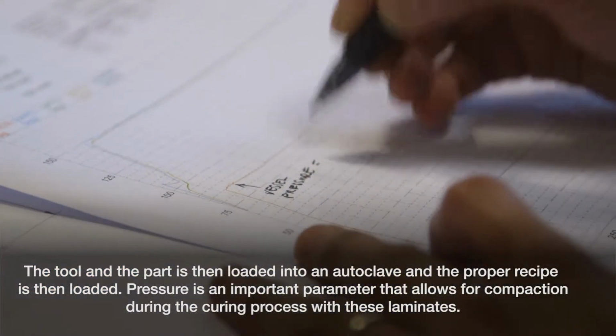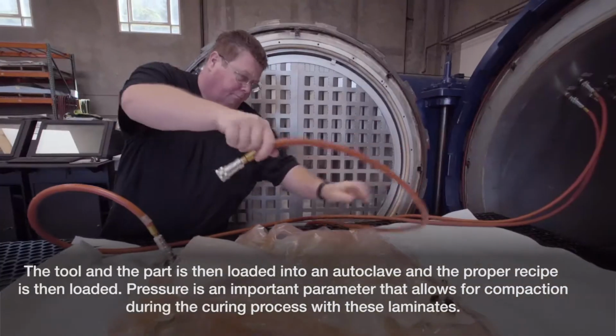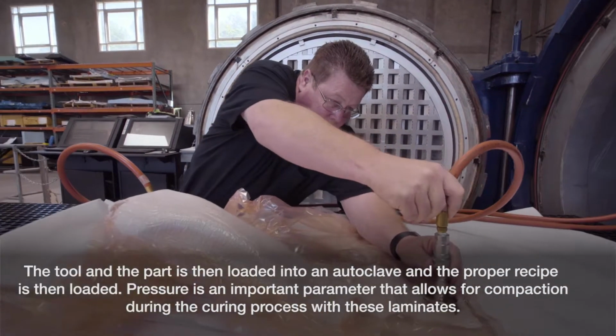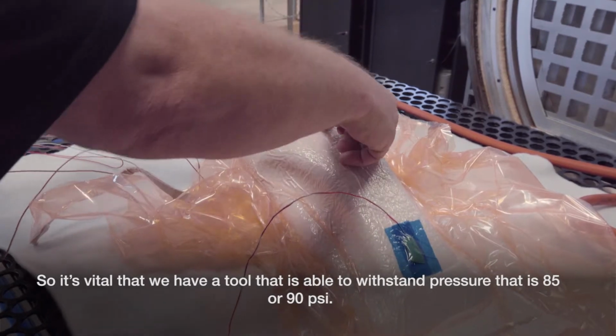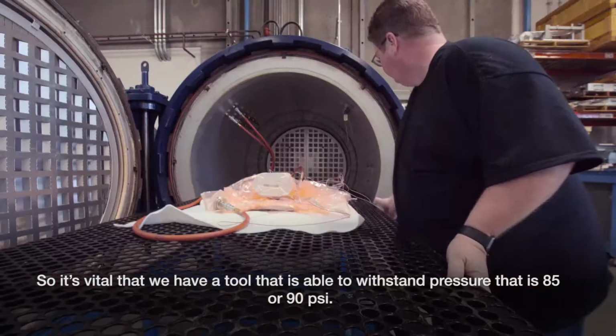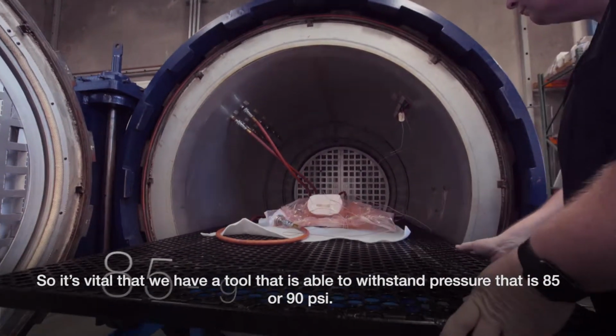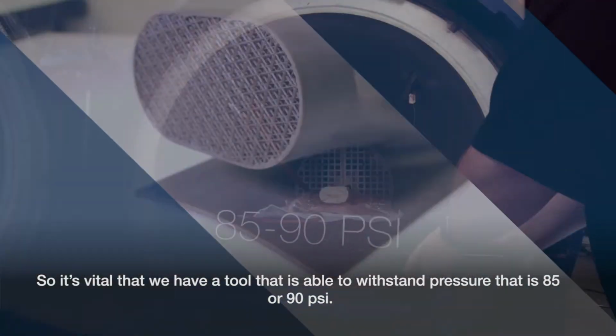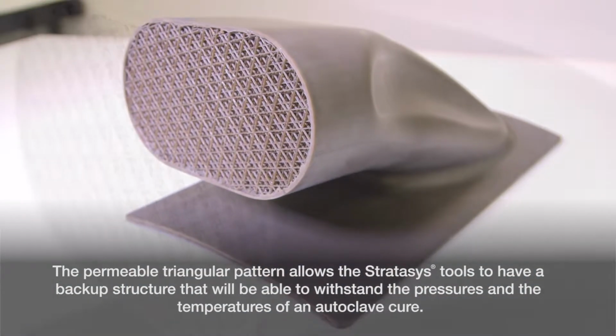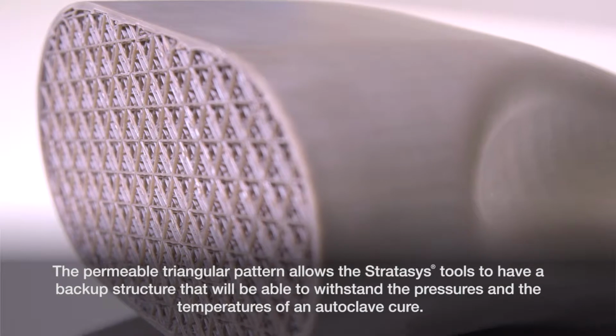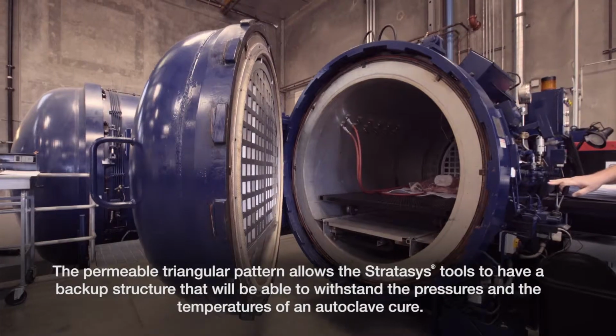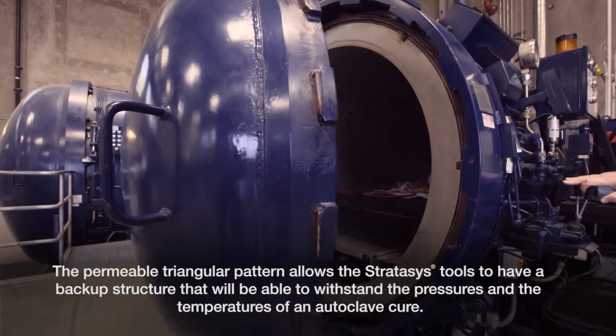Pressure is an important parameter that allows for compaction during the curing process with these laminates. So it's vital that we have a tool that's able to withstand pressures that are 85 or 90 psi. The permeable triangular pattern allows the Stratasys tools to have a backup structure that will be able to withstand the pressures and the temperatures of an autoclave cure.